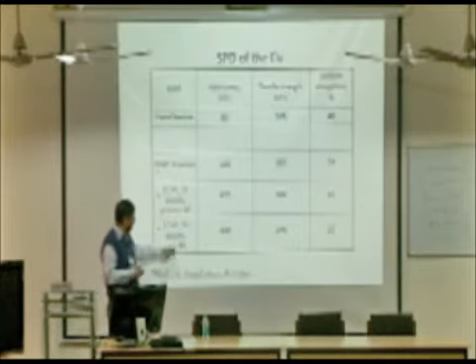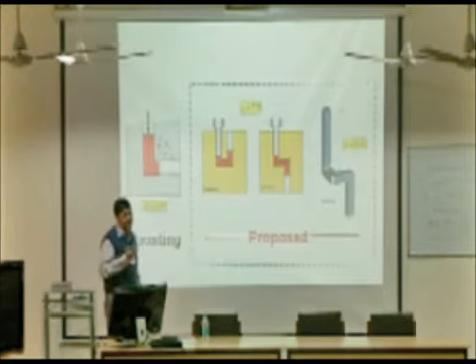These are results taken from literature: the original copper specimen had a yield stress of 80 MPa; after 2 ECAP passes we achieved 320 MPa; after 16 passes even higher — with and without back pressure shown. Our main aim is to commercialize this process. Because if we are repeating 16 or 20 passes on a 10–20 mm billet, it will be very time-consuming. So if we can redesign the ECAP process such that in one pass we achieve a higher equivalent strain — rather than 1.15 per pass requiring multiple passes to reach 3.45 — that is the goal.